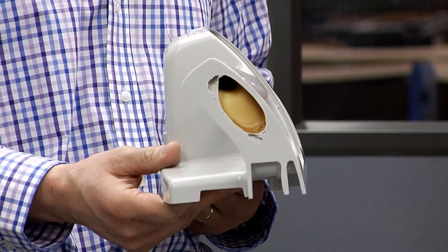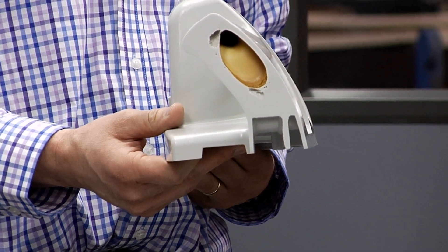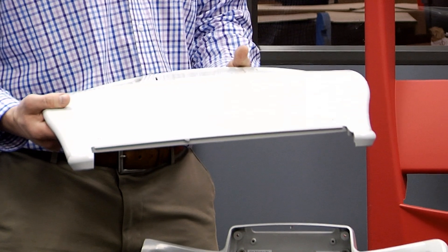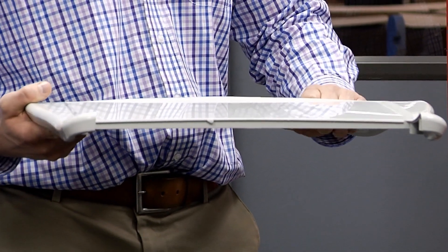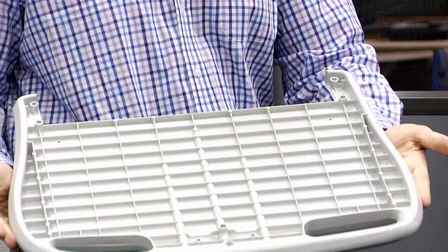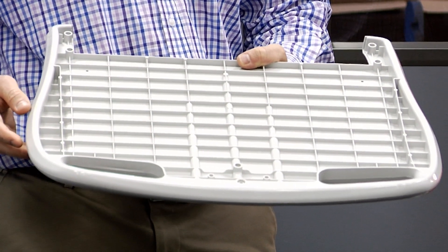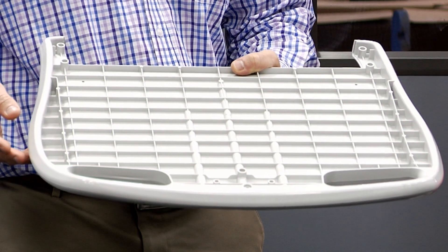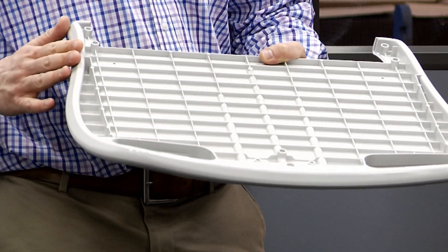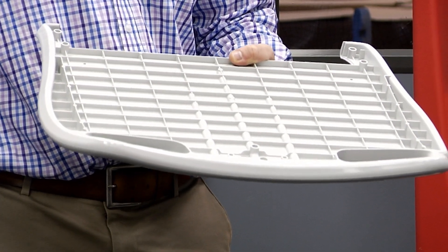Here at Sager, we use two methods of gas: nitrogen gas and also a newer method using carbon dioxide, which allows you to cool the inside of the part. This other part is also a consolidation part — we call these a handle-panel part, where you combine a handle and a panel. There's a work surface and two handles. On the backside, gas channels run down both sides for stiffness. Using gas-assist, you don't have to core out the part — you can leave it solid and just gas it out, which allows practitioners to clean the surface much more easily and helps hospitals reduce nosocomial infections.